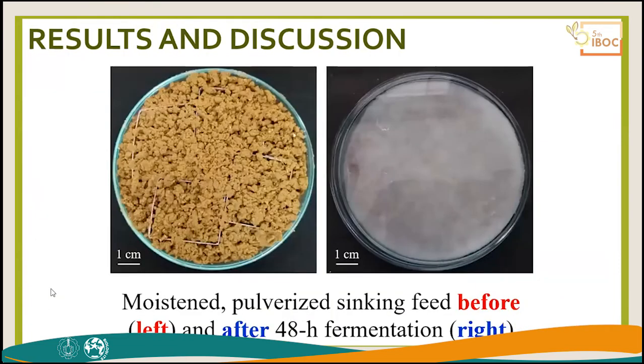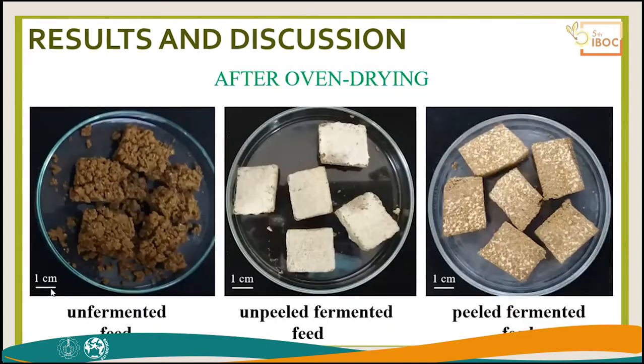So this is the macroscopical appearance before and after fermentation, and this is after 3 different treatments. On the left is the feed without any fermentation, so just oven drying. As you can see here, the particles making up the feed broke down easily. And then in the middle and on the right, as you can see, the structure is preserved.